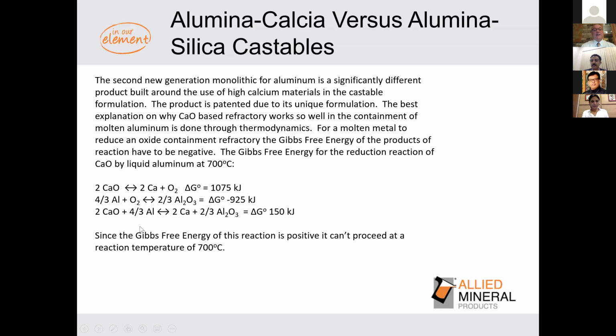You can see here, 2 calcium oxide plus 4/3 aluminum will give 2 calcium plus 2/3 alumina, but the Gibbs free energy is positive, and only a negative Gibbs free energy would allow the reaction to go from left to right. So if it's positive, this cannot happen at 700 degrees C. So that's why we developed the refractories with calcium.